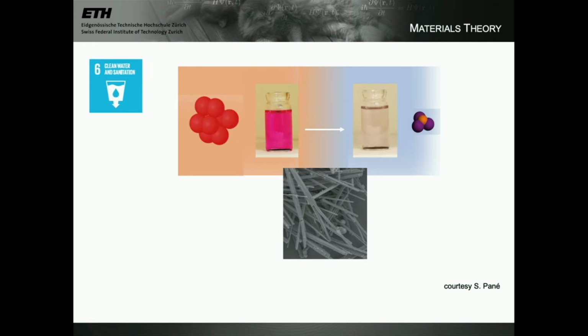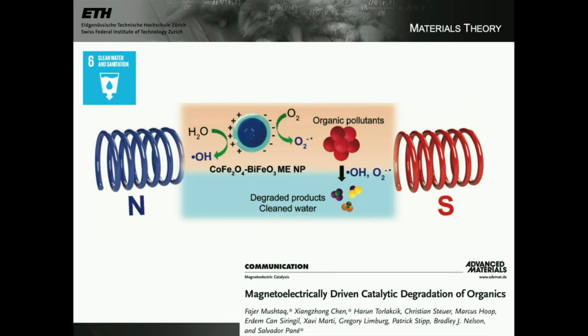Salvador has been able to demonstrate that nanorods, nanoparticles of bismuth ferrite, can take large, nasty organic molecules. This is a rhodamine B molecule. And when they're shaken using magnetic fields, they can break down these nasty molecules into little molecules like water and ammonia. The mechanism we believe is occurring is that one has a bismuth ferrite particle, and it's ferroelectric, so one side of it is negatively charged and the other side is positively charged.